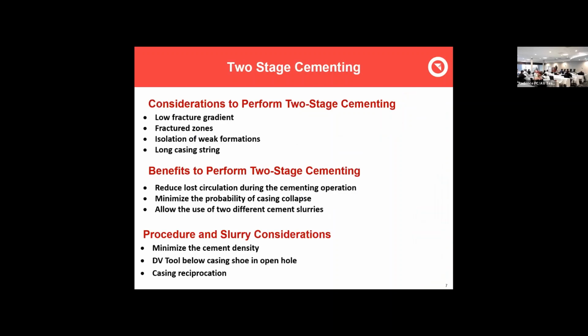So our considerations, like I mentioned, low fracture gradient, fracture zones for doing these two-stage jobs. Some of the benefits we've had, especially in that second stage, we have very minimal losses, even though we are somewhat in open formation. We've had minimal losses during that second stage, and ideally, it's just to minimize the potential for issues in the casing to casing annulus, to make sure we get a good cement job in that section.